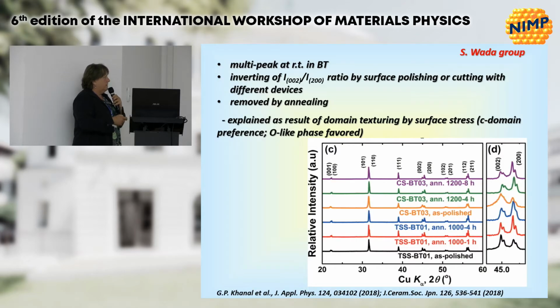And another very nice study from 3 years ago, from the group of Wada, in which not only did they show that by increasing temperature you can induce the orthorhombic state or multi-phases, but they observed that some states, some symmetries, can be induced even by cutting or polishing the ceramic, and this can be removed after annealing. Here there are a few samples just polished or after annealing for 1 hour, 4 hours, and many hours, and so on, or sintered by different procedures. And this has been observed also by us.